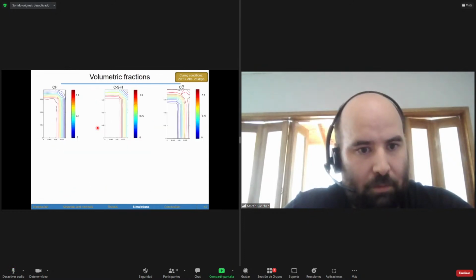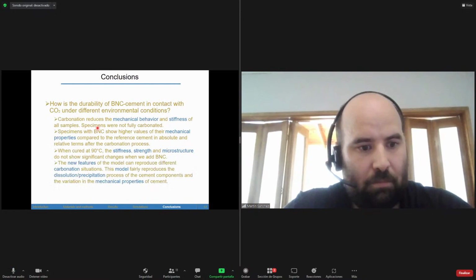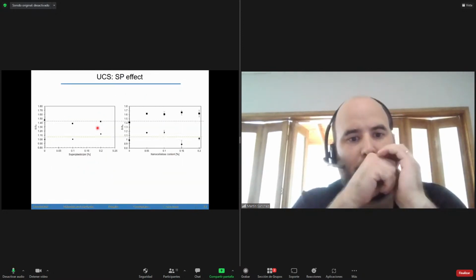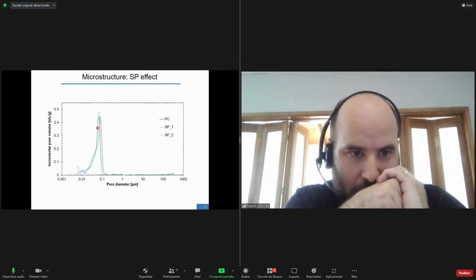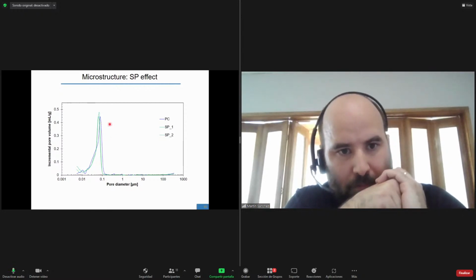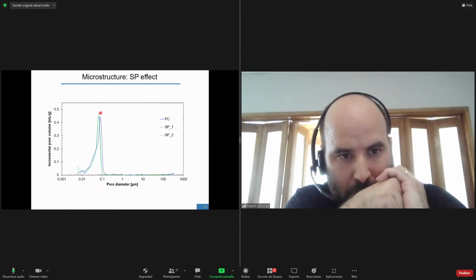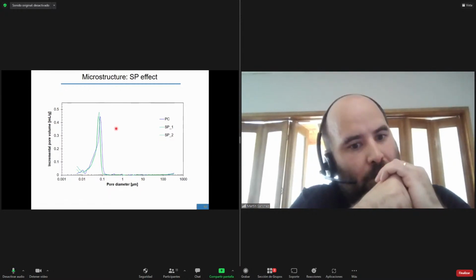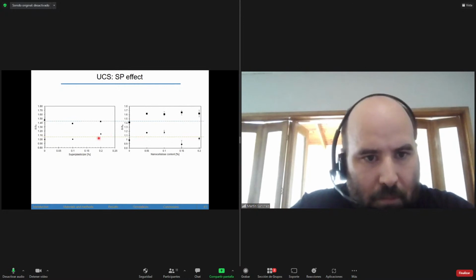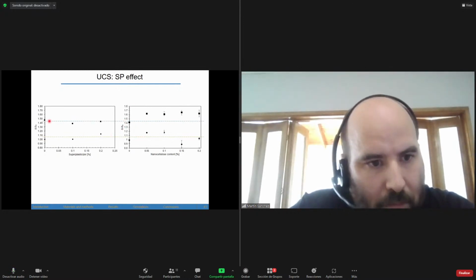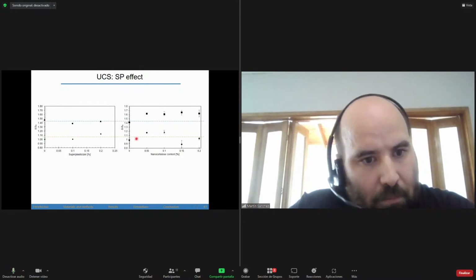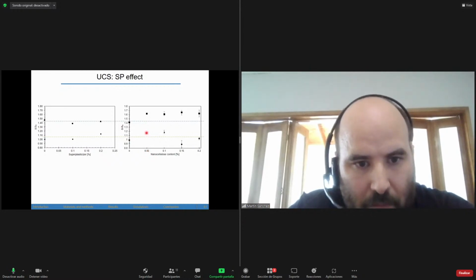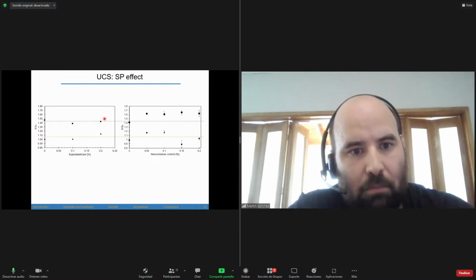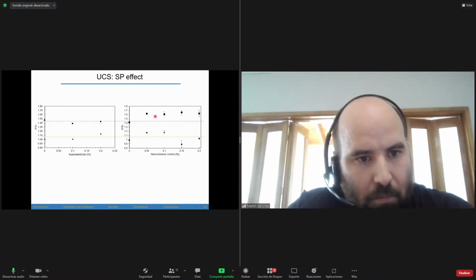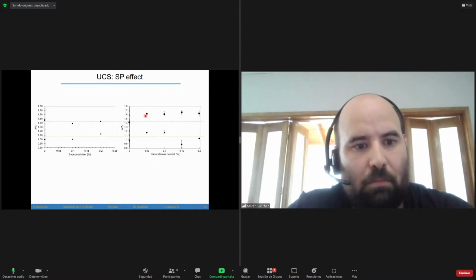Yes, let me. All right. So we performed this. We analyzed a little bit that problem. We saw, for instance, in the microstructure, it did not change too much the porosity or the pore size distribution, and we also saw that for some amount of superplasticizer, the difference with the samples carbonated with bacterial nanocellulose was not improving mechanical strength, but with nanocellulose it was increasing the mechanical strength.